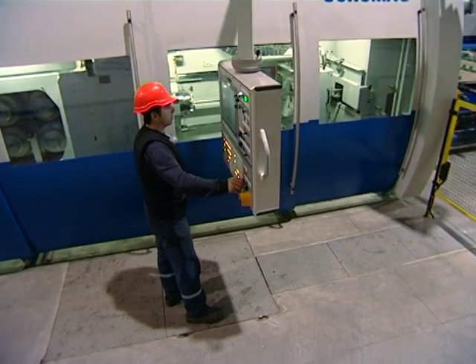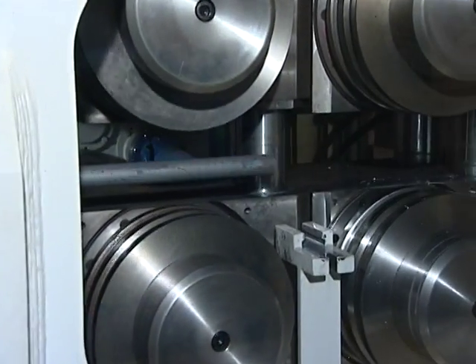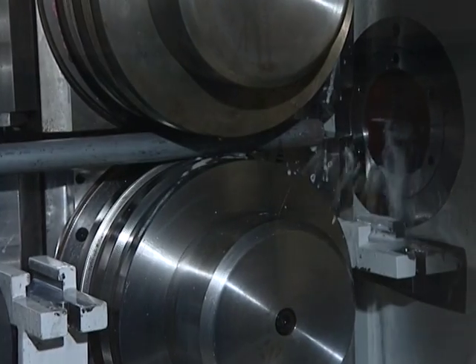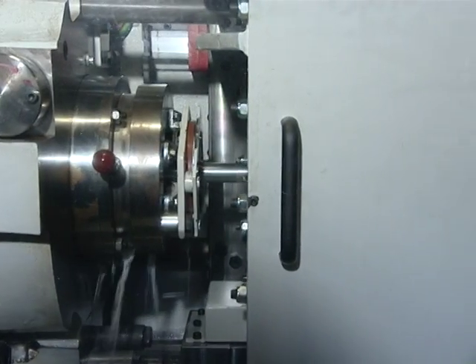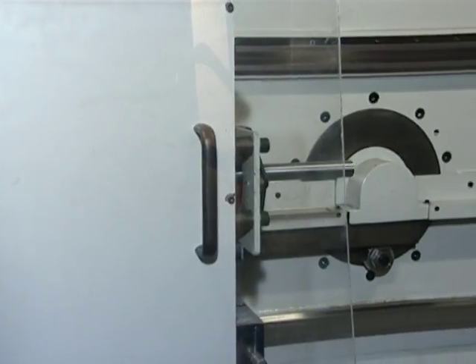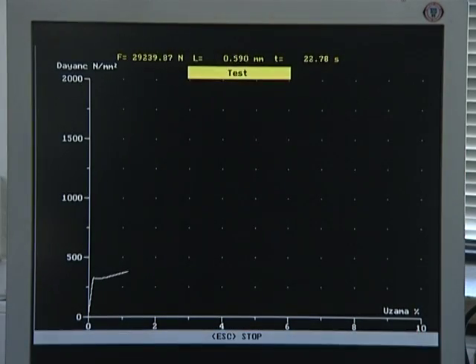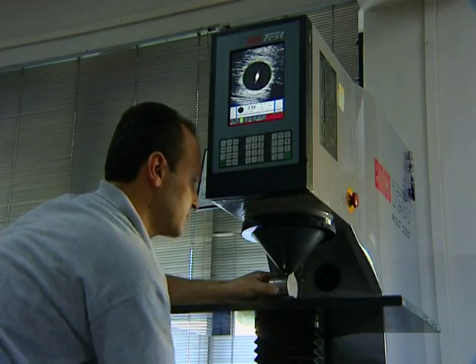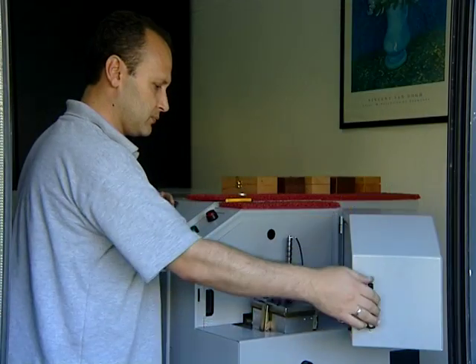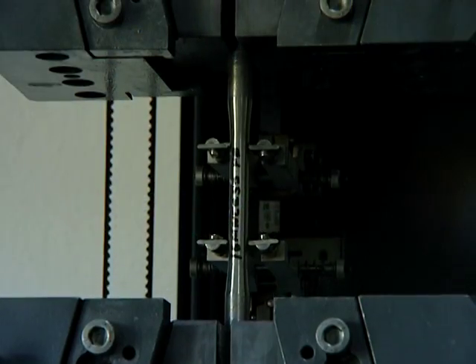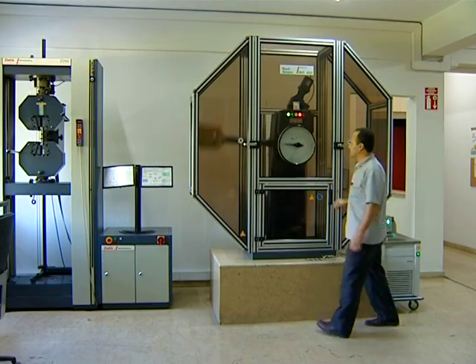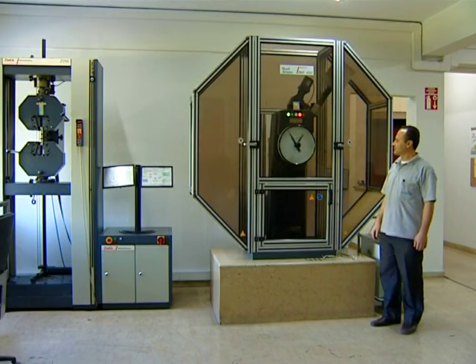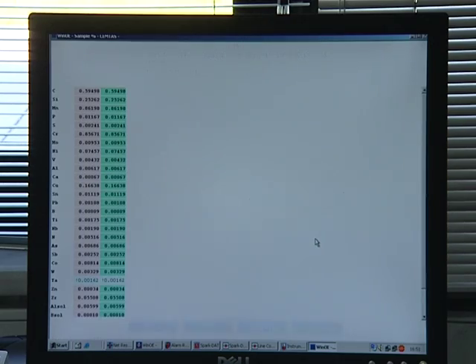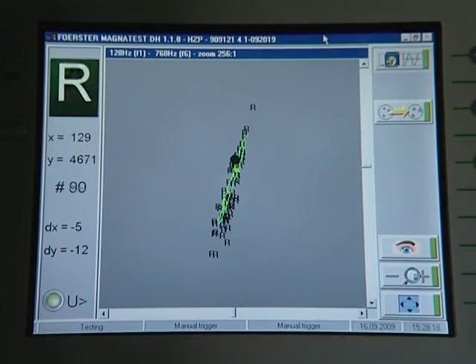In the peeling line, the operation is performed with maximum 6-micron RZ surface roughness and H8 tolerance capability. During production, chemical analysis, hardness, oxygen, nitrogen, and sulfur measurements, tensile, notch impact, hardenability, and microcleanliness tests are carried out in accordance with the relevant standards in advanced steel laboratories. The steel is now ready for stabilizer bar manufacturing.